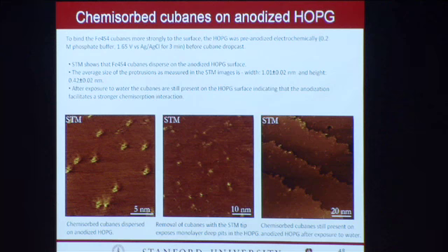And so what we've been doing is we've been trying to change that surface, that graphitic surface. We're trying to pit it just slightly enough to get these cubanes to anchor themselves down, but not so much that we cannot get atomic resolution, because we want to be able to count how many cubanes we have on the surface. And that's exactly what we were able to do by anodizing the surface, by applying a positive potential. We were able to create these little pits and anchor the cubanes down. And in fact, when we bring our STM tip very close to the surface, we can even kick the cubanes out of their pits, and we can see the dark pits left behind. This is after immersion in water, and you can see that the cubanes are still present on the surface.